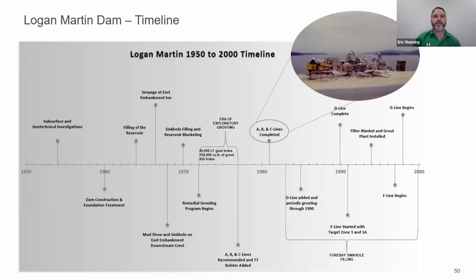They just identified areas that were geologically significant that may have weak points in the original grout curtain. The grouts that were used in the original grout curtain would be considered unstable and erodible. And during that era, from roughly 72 to 77, there was approximately 80,000 linear feet of grout holes and 194,000 cubic feet of grout that had been injected in about 456 holes.